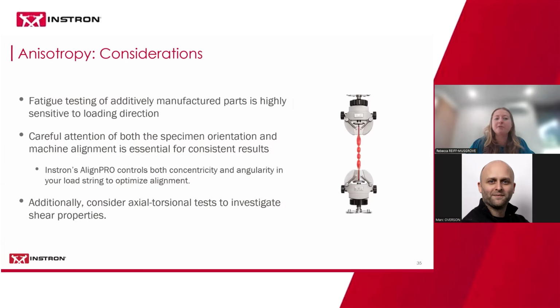So at Instron, we have something called the AlignPro that helps control both the concentricity and angularity in the load string. Again, making sure that any change in alignment is from the material itself and not the test machine. Additionally, people often will consider axial-torsional tests to investigate the effects of the differences in directional properties. So things like the shear properties we can look at if we do axial-torsional tests. And this is something that we often see, and we often supply biaxial machines with tension and torsion to investigate these properties.